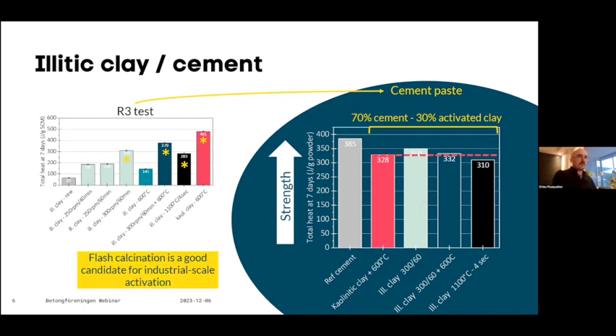And in all of those methods, actually flash calcination is something that is doable at industrial scale. So it looks like a perfect match to activate this type of clay. Especially, as I said, we can still optimize those parameters and reach something even higher here.